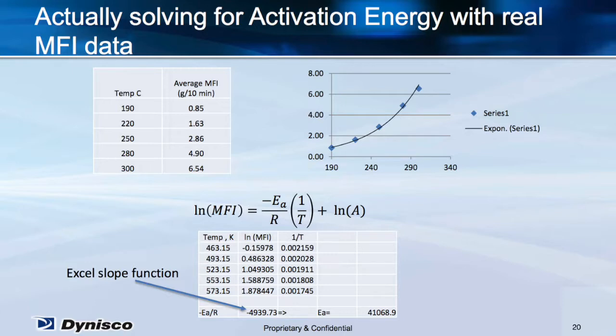On this slide, I am showing how to calculate the activation energy. First, in the upper left-hand side of the slide, I asked one of our field service guys to take some LDPE we got from a recycler and run it in a melt flow indexer at various temperatures and record the MFI. He actually used this experiment to also train a brand new field service employee on how to run the indexer. So they ran the material at 190, 220, 250, 280, and 300 degrees Celsius. And at each temperature, they recorded the MFI readings, as you can see in the table. To the right of that table is the MFI and a standard fit to an exponential from Excel.